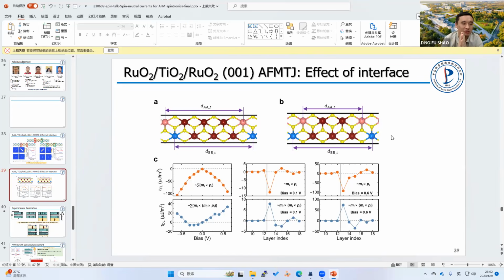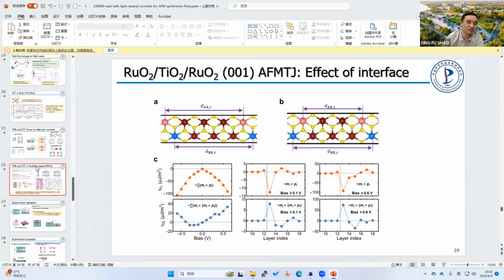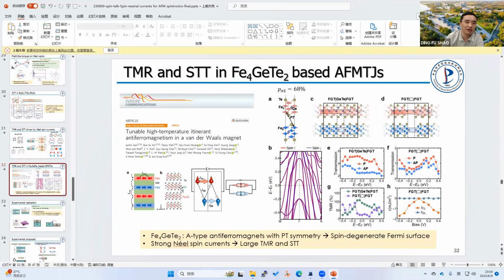And we found that even if we use a very large broadening, like 1 eV or 0.1 eV, we still have a very strong effect. So I think this is quite straightforward, and at least for this case it's very understandable, because in this case we have a totally spin neutral current, but the ferromagnetic sublattices are well separated. So if we consider these tunnel junctions or some other devices as parallel connected ferromagnetic layers, and if the effects in each ferromagnetic layer are robust against the disorder, the effects will be robust in total. I don't know if this answers your question.